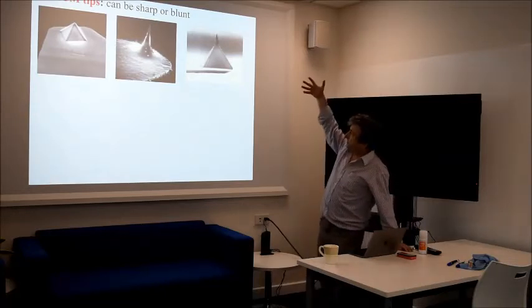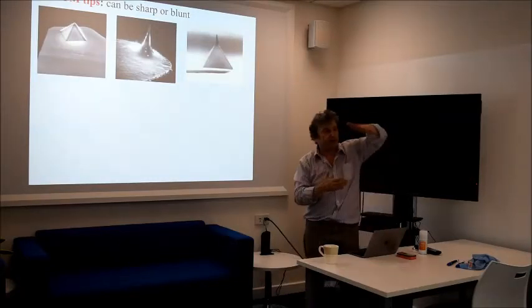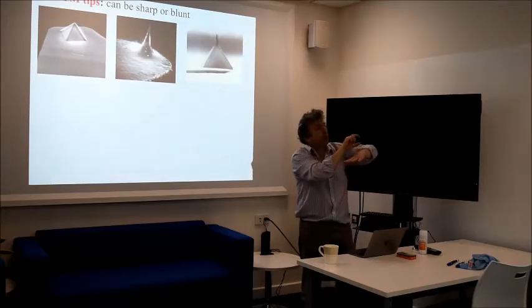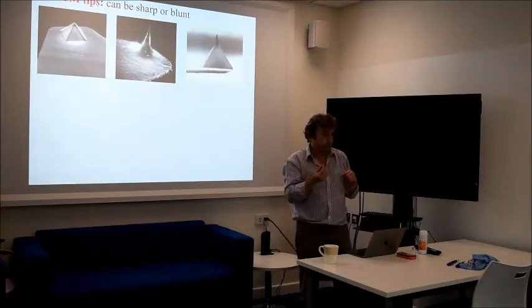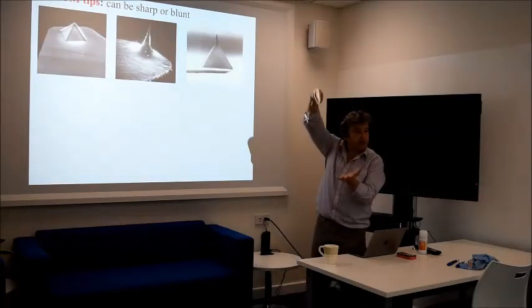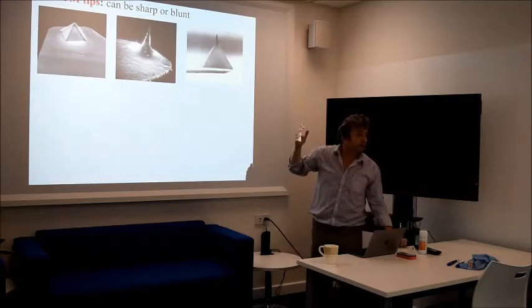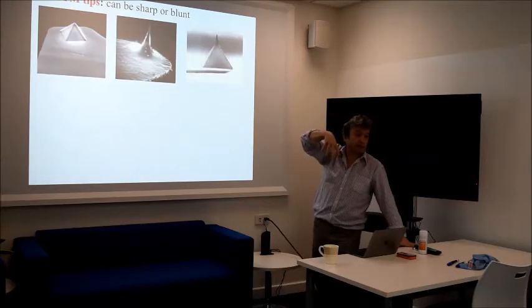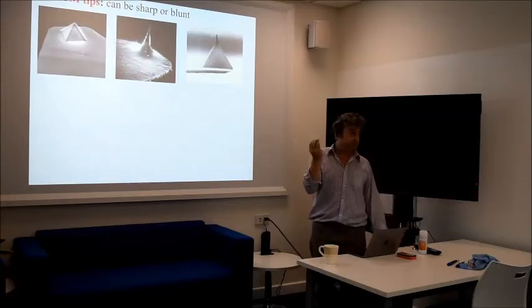First, they create a protrusion on the surface of the cantilever. You have a cantilever which actually moves, and at the end of the cantilever, you have a piezoelectric. You apply a bias voltage on this piezoelectric, and it would move the tip by a little distance, depending on the voltage you apply. But you have to make something really sharp at the end. They do it by bombarding the tips with argon ions, for instance, or putting the tip in some kind of solvent. And after that, you still can't guarantee that the tip is really atomically sharp.